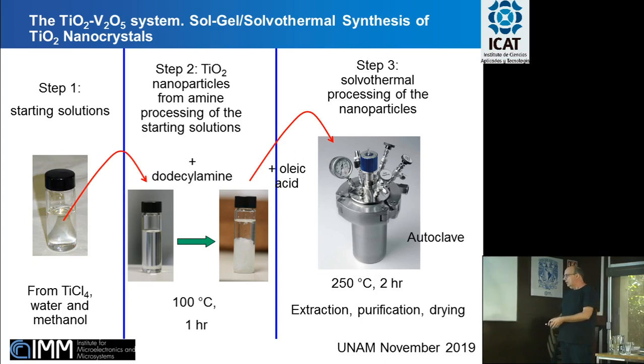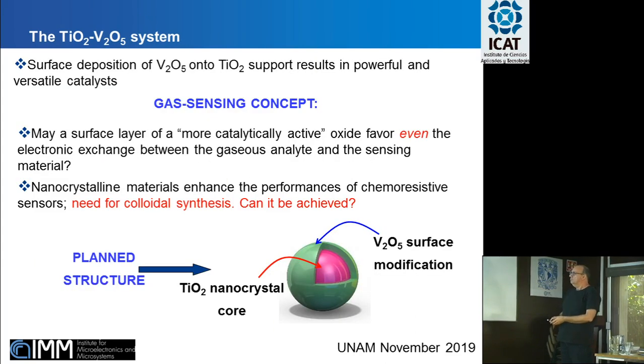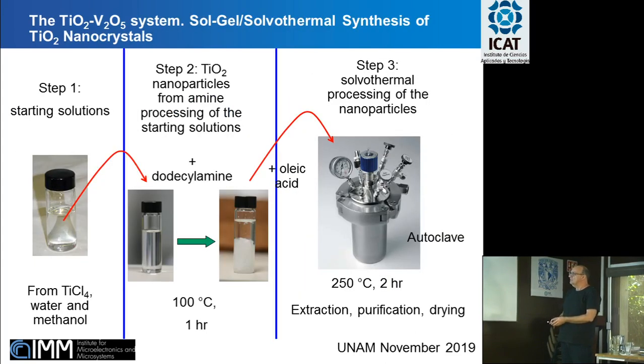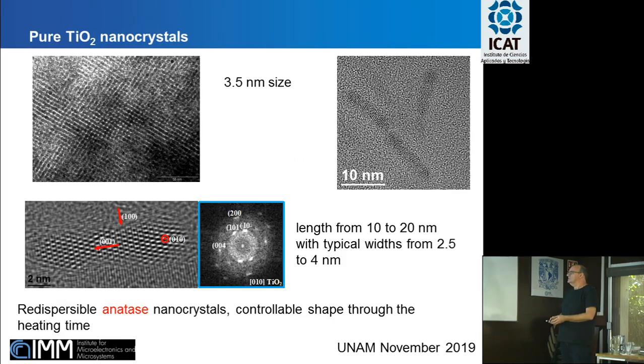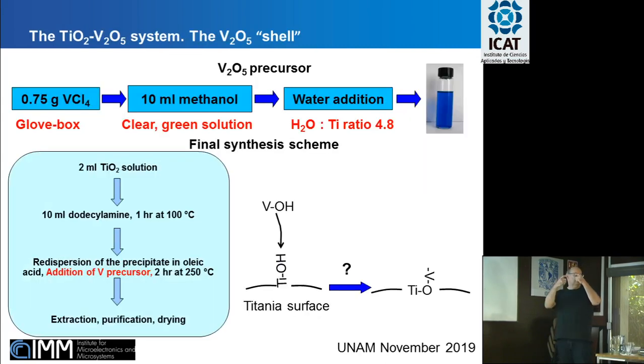But we know how to do the core. This is the case of titanium dioxide. This is the processing that I was showing before. Our solvothermal process, precipitation, dodecylamine, solvothermal processing, and so on. These are our titanium dioxide nanocrystals. And now, we would like to make some deposition of vanadium oxide onto the surface.